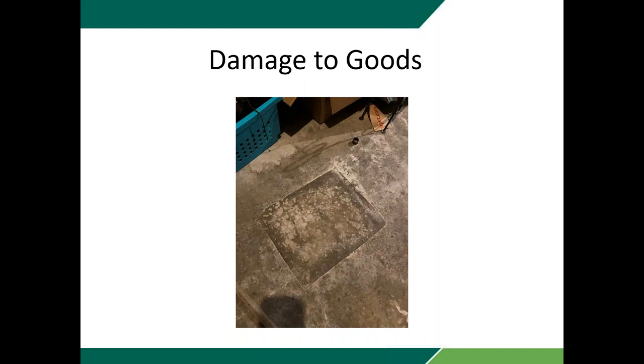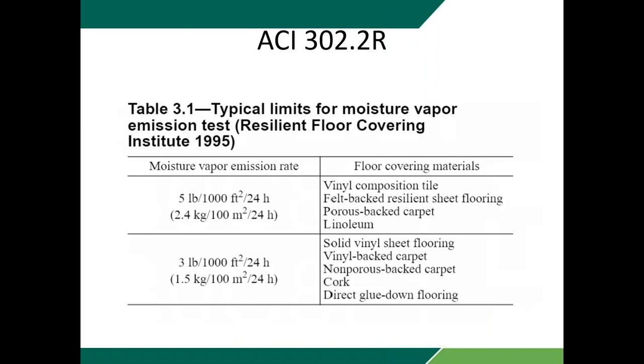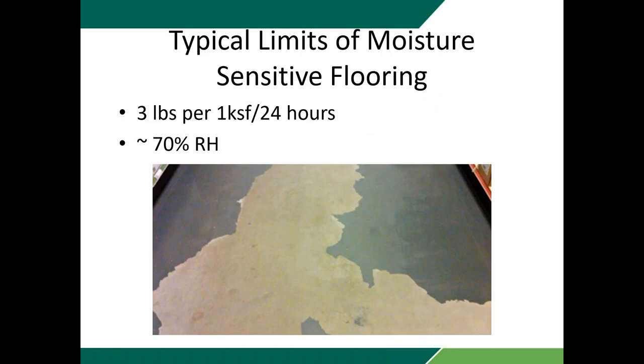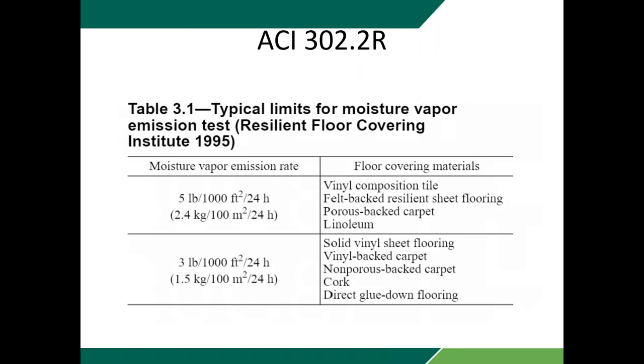So there's a lot of sensitivity out there with a lot of the coatings. For the most part, the typical limits of moisture sensitive flooring are going to be 3 pounds per 1,000 square foot of moisture drive, or moisture vapor emission rate, referred to as MVER in a lot of cases, or a relative humidity of approximately 70% in the slab. And we'll talk more as I get into the testing of how we determine what those moisture levels are. But those are probably the two key numbers that manufacturers of sensitive flooring are looking for: a maximum of 3 pounds per 1,000 square foot in 24 hours of moisture drive, or a maximum relative humidity of 70%.